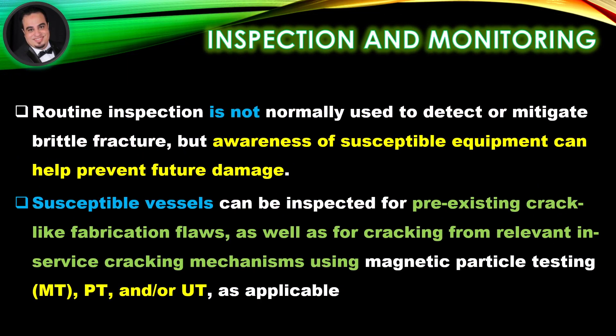Inspection and monitoring: routine inspection is not normally used to detect or mitigate brittle fracture, but awareness of susceptible equipment can help prevent future damage. Susceptible vessels can be inspected for pre-existing crack-like fabrication flaws, as well as for cracking from relevant in-service cracking mechanisms, using magnetic particle testing, liquid penetrant testing, and/or ultrasonic testing, as applicable.